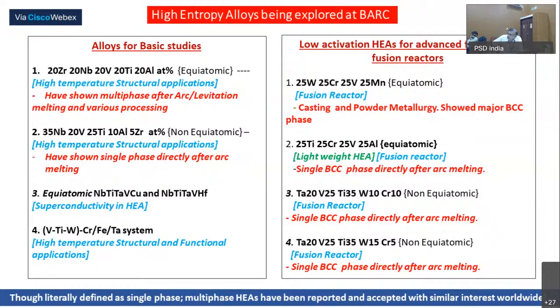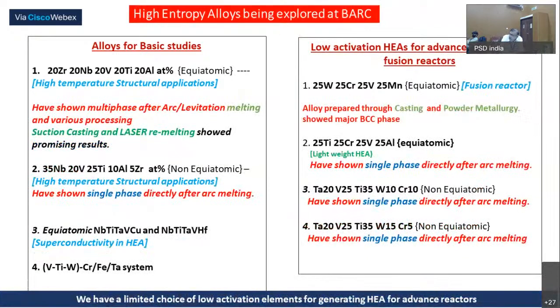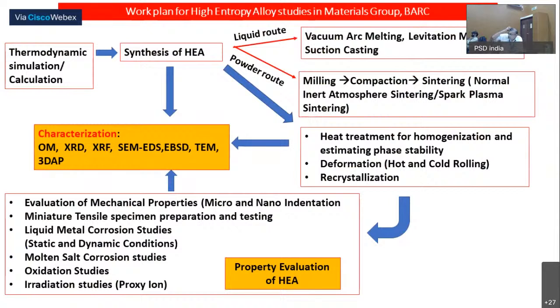For example, the first alloy series we did by casting as well as by powder metallurgy route. The second series of alloy we have shown the single BCC phase which we could get directly after melting. See, in the entire high entropy alloy field, the mother of the problem is to find the single phase alloy, and then you can work on that. So this is some of the preliminary work which I wanted to show here on the high entropy alloy. And let me take you to the next of that is what we did.